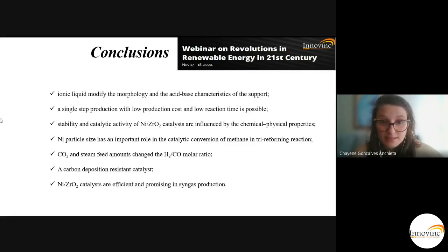Also, we have a catalytic activity and stability of this type of materials which are directly influenced by the chemical and physical properties. Nickel particle size has an important role in the catalytic conversion of methane, and the most important characteristic of this type of catalysts is related to the nickel particle size. The lower the nickel particle size, the higher will be the conversion of methane and CO2. Also, when we change the CO2 and steam feed, we could change the molar ratio of the syngas.